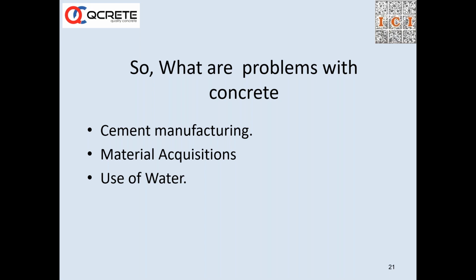The other aspect of OPC production is, we have seen over the years that it is not the cement content which is important, it is the water cement ratio which is important. So at lower water cement ratio, by judicious mix designs, we can get the strengths that we want, and the modern admixtures that we have today have been able to push the water cement ratios easily to a level of 0.22, 0.23 and things like that. And hence, at lower cement contents, we can get higher strengths and higher durability. There's no problem with that. So we should be concentrating on the lesser usage of OPC.